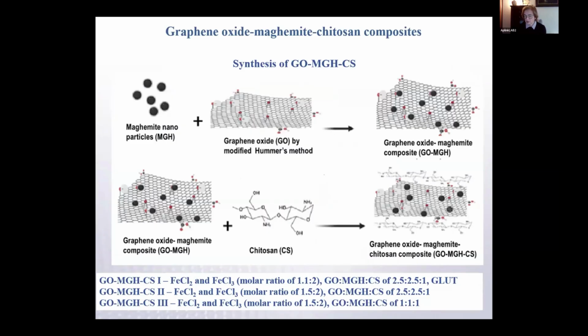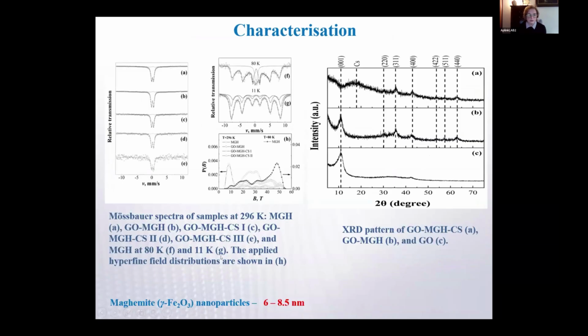So graphene oxide maghemite chitosan composites were synthesized using slightly different methods. The first sample was synthesized using glutaraldehyde, but in the two other samples we don't use glutaraldehyde for cross-linking. Samples were characterized using Mössbauer spectroscopy. X-ray diffraction analysis was performed also, and nanoparticles in samples were identified, and their size varied between 6 and 8.5 nanometers.